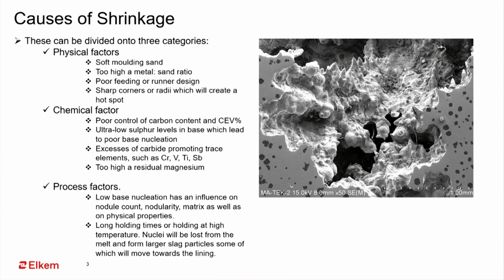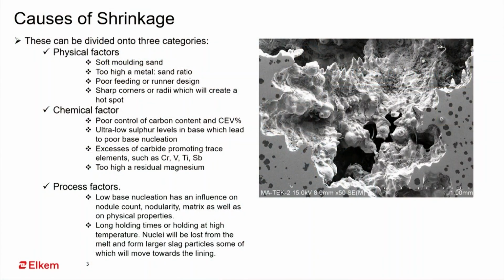The chemical factor is mainly the carbon equivalent, and especially the carbon content. Another is the low sulfur content in base metal. Some foundries are using very high purity raw material, and sometimes they are facing a very low final sulfur level. But in the case of ductile iron, you need a certain minimum level of sulfur, at least 0.005%. Sometimes because of raw material changes, a lot of trace elements are also creating a lot of metallurgical defects.